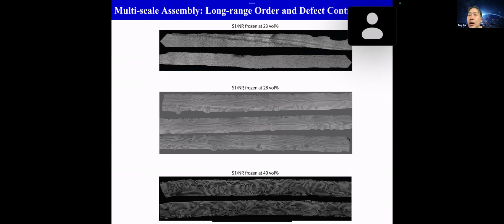So I'm going to show you a few things. The processing is so simple. We cast it and then we dry it. And the only parameters we have to deal with are at what concentration it will start to dry quickly and how long it will stay at a certain concentration. If I can take your eyes to it, you can see that at 23%, obviously the microstructure is now forming. We get nanostructures, even though this is rapid solvent removal, indicating that nanostructure formation is really governed by short-range diffusion. It's very quick, so you shouldn't spend your time to generate nanostructures.